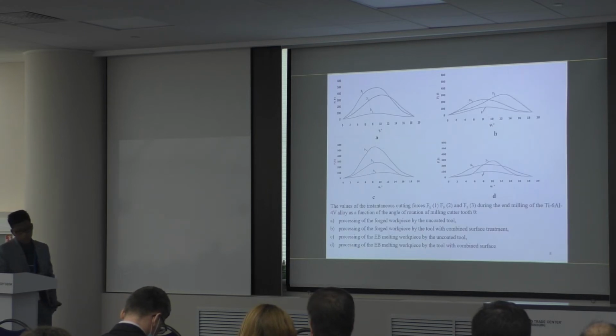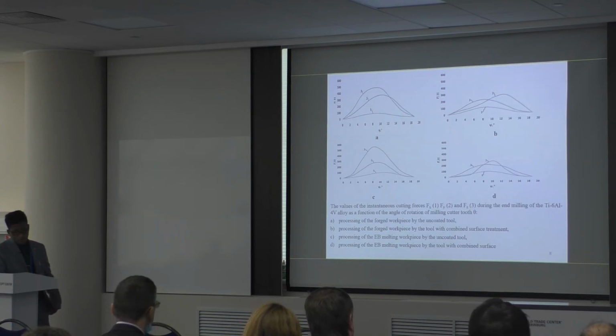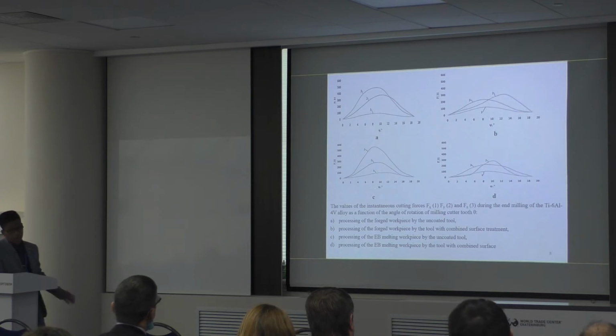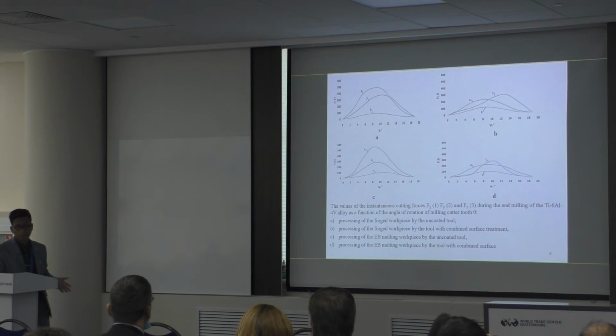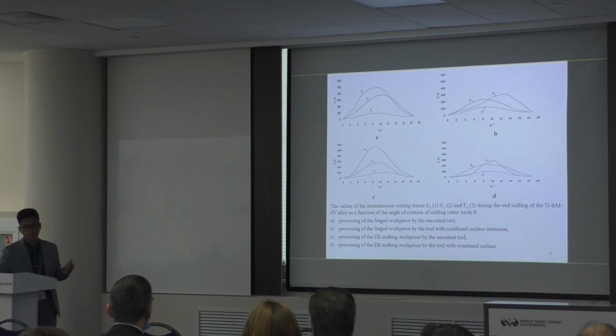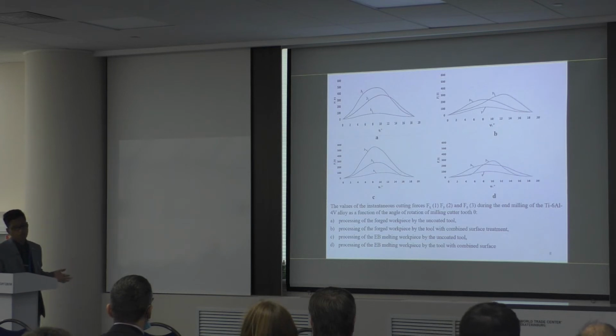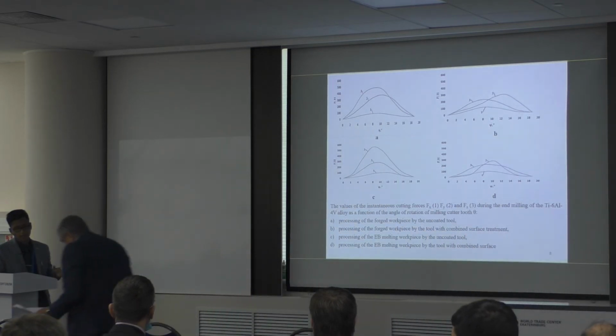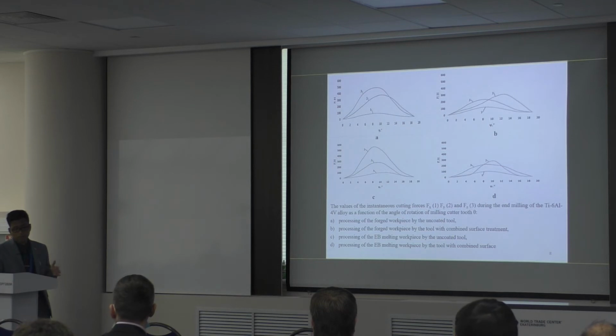We can show figures A and C. In comparison, figures A and C give an idea of how significantly the structure of the titanium alloy affects the components of the cutting force. When milling a workpiece obtained by electron beam method, the cutting force Fz increased by approximately 50%. At the same time, there is a 20% drop in the force Fy.